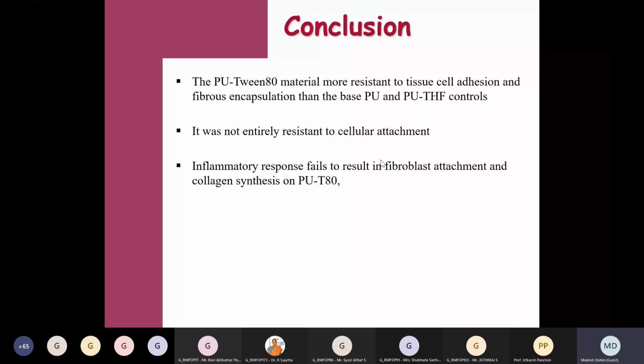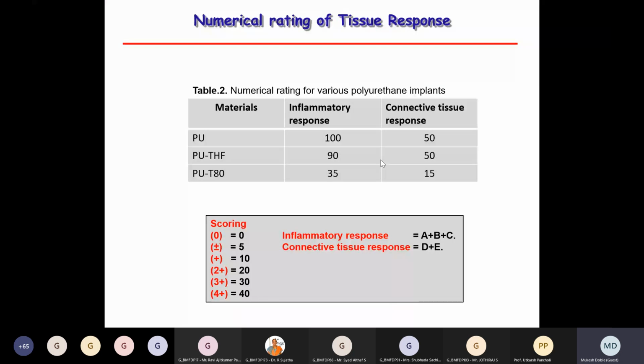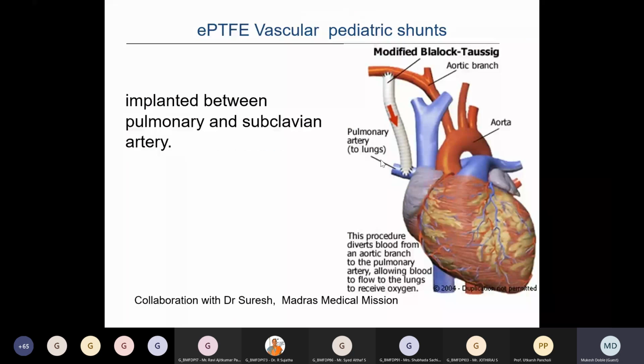So the modification, based on the in vitro studies, we have proven that it's able to prevent the bacterial attachment of different types of bacteria, and salt incrustation, as well as reduce the inflammatory response by almost a factor of 3. So we have tried to identify a new surface modification technique which could prevent bacterial contamination of this polyurethane urethral stent, as well as prevent the salt incrustation. At the same time, we are able to reduce the inflammatory response. Okay, so that's one problem.